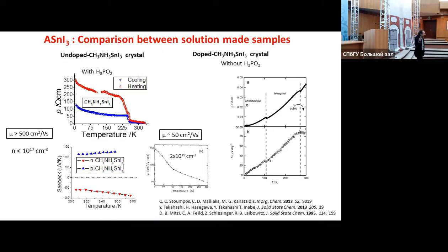Tin has a very, very special property. When it oxidizes and goes from the 2+ state to the 4+ state, it maintains the same coordination environment. That means the structure remains roughly the same, so it's very easy to oxidize. But you need to take very special care, and we use this reducing agent to revert the oxidation from 4+ to 2+, which is responsible for the p-type doping in the material. And we managed to keep it to as low a threshold as possible, obtaining large mobilities. So the numbers are not very accurate, because these materials are very difficult to make and extremely sensitive to handle. But still, we have been able to demonstrate that there is some large difference from the use of reducing agent or not.